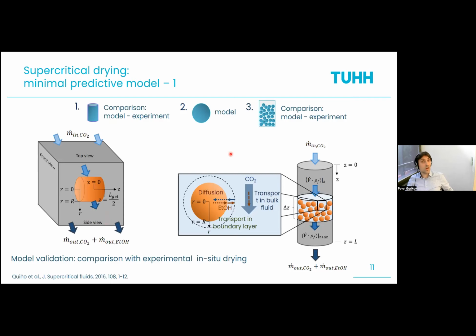Then you may also say, okay, what about particles? In many cases, I need particles. So maybe one particle is a little bit too small. What happens if I put the particles in a fixed bed? Then you can also do an experiment with fixed bed particles and see how fast the drying goes. With all these three cases, you can be pretty sure that you can basically describe any geometry you want. And as I just mentioned, in some cases you have to use advanced analytical techniques, which in our case was Raman spectroscopy, to resolve the profile and later on to validate the model.